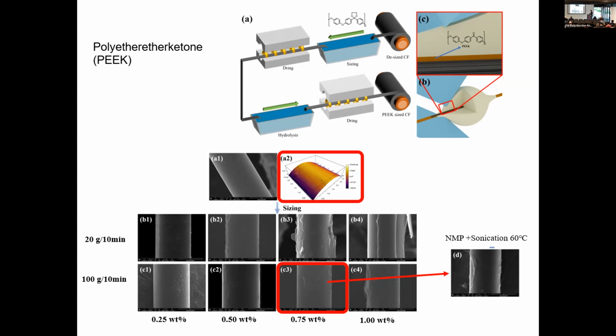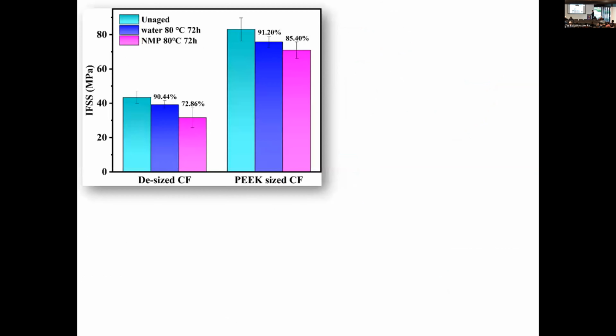Certainly there are some challenges, because PEEK is mostly not soluble. So you need to create an intermediate phase first, and then finally after hydrolysis, you go back to PEEK. So that's the sizing. We successfully created the PEEK sizing on the carbon fiber. The difference here: without sizing, you only got 40 megapascals, and now you can get 80.